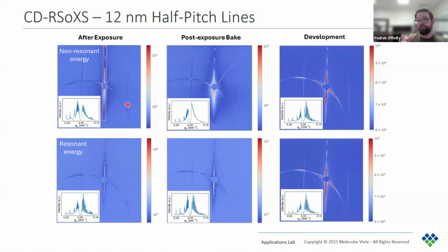So this shows that PiFM results are confirmed by CD-RSoXS, but also that PiFM can predict artifacts that will be in the developed sample just from imaging the exposed sample.